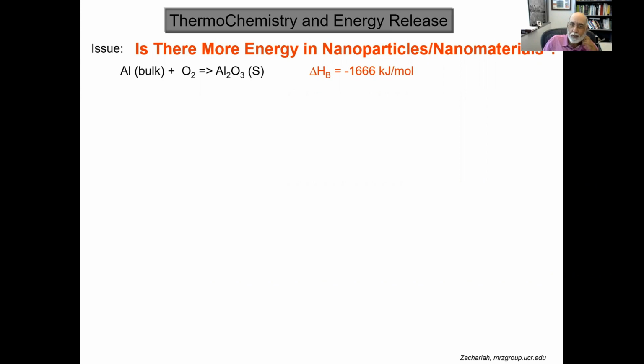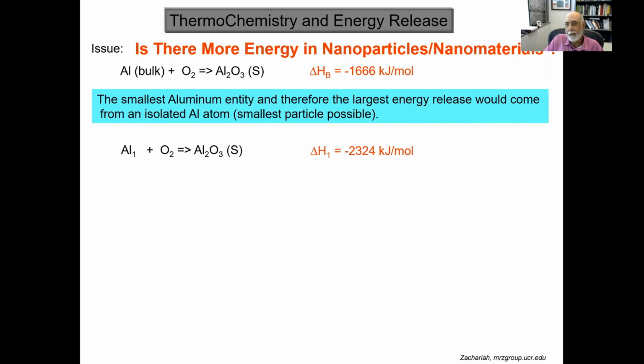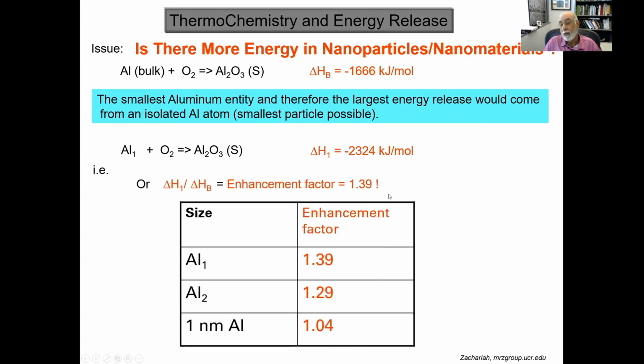So what's the smallest nanoparticle I can make? Well, it's really not a nanoparticle, but let's first do standard thermodynamics. If I look up in the JANAF tables, aluminum bulk plus oxygen gives you this much energy. This is delta H of reaction. And again, if I wanted to do a nanomaterial, what's the smallest entity I could imagine? Well, actually, it's a single aluminum atom. And if I look up that thermo, I get this number. And the ratio of these two is 1.39. In other words, the difference between these two is only 39%. And by the time I get to a 1 nanometer particle, I only have 4% more energy.